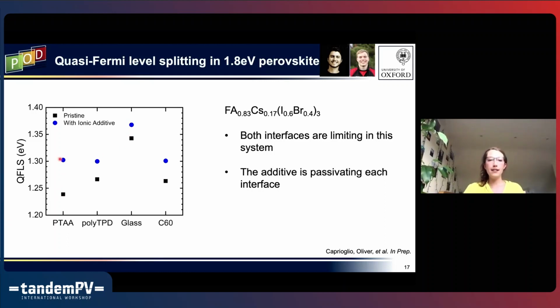And that effect is even more drastic actually with the contact layers. So kind of two things to pull from this graph. First off, both of our interfaces on both sides of our PIN device for these wide band gap materials are slightly quenching. So we get slightly worse quasi-Fermi level splitting when we use them. But this ionic additive seems to be helping to slightly passivate those interfaces.